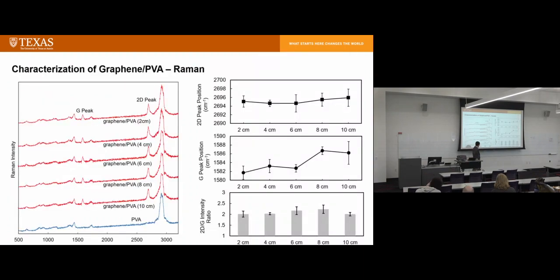So we looked at the Raman shift of all the samples. This is the Raman after transfer, Raman shift of graphene on PVA. So we transferred graphene onto PVA, another type of material we transfer onto. It turns out it's not very easy to get Raman peaks for graphene on PVA, because PVA on its own has Raman peaks, and so all those peaks are contaminated by this.